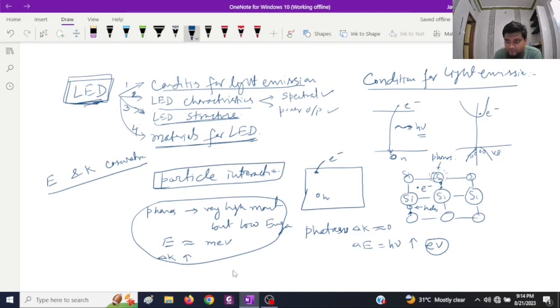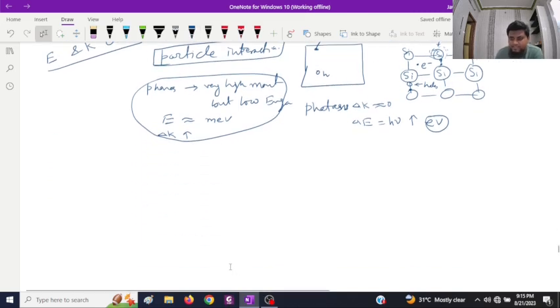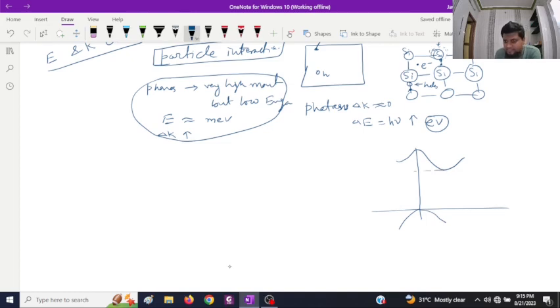If the electron which is falling can find the holes at the same momentum, of course, for this transition we don't need any change in momentum, delta K is approximately equal to 0. So in this case, this transition will emit a photon. However, if you see the band structure of silicon, which is unfortunately like this, the minimum of the conduction band and the maximum of the valence band don't lie on the same momentum vector K.